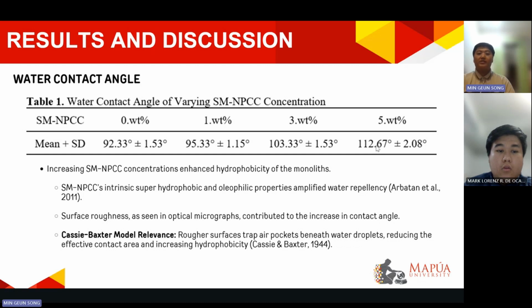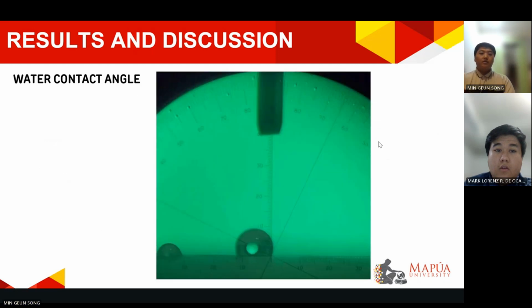The relationship between surface roughness caused by the NIPS process and hydrophobicity can be described by the Cassie-Baxter model. According to this model, rough surfaces amplify hydrophobicity by trapping air pockets between the water droplet and the surface, reducing the effective contact area of water with the sample. Here is a sample of our water contact angle results. Here we can see that the approximate WCA reading is around 115 degrees.